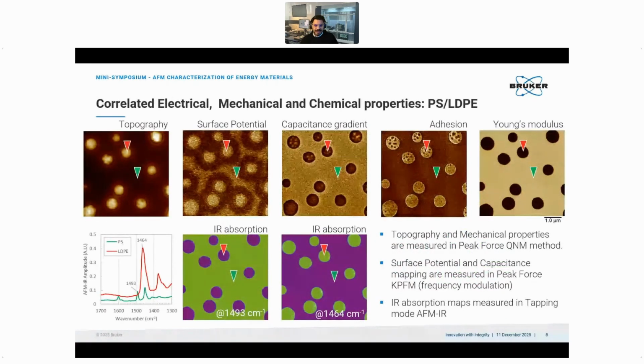And this is exactly what I want to show. So these results here are made on a typical, we call it a reference sample, because it allows us to put forward these features of the measurement and the modes. So this is a blend of polystyrene and LDPE. The polystyrene is the matrix, and LDPE are these bubbles, basically. So we know what the sample is made of in that particular case.